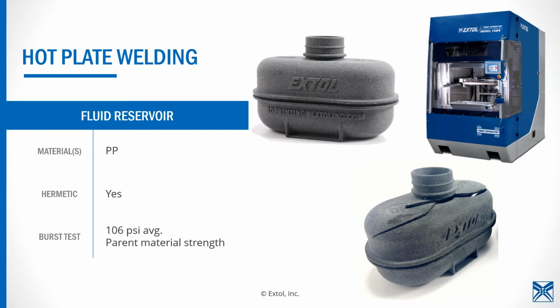So you can see here, I love this burst picture here. It's a great example of how not only did that weld hold up super well, and we actually had failure not on that weld line, but it's showing, up to 106 psi, we are able to have that airtight seal in our material, which is very hard to do in 3D printing, up to the point where we're actually bursting the material.